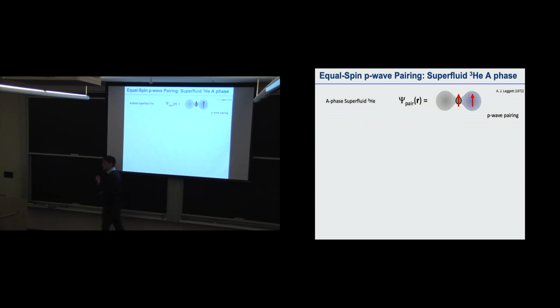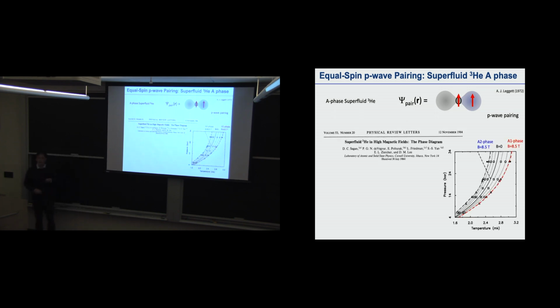Especially in this A phase of superfluid helium-3, it shows quite intriguing transitions under magnetic field. When you apply a magnetic field to this superfluid helium-3, you immediately see two transitions appear - one transition goes to higher temperature, and the other transition goes to lower temperature.